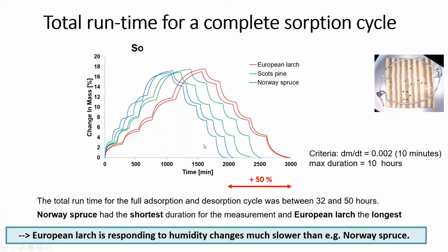Okay, so what I'm presenting, some of the highlights that you found that are quite interesting to think about. Like, how long does it take to complete a sorption cycle? So what she has done is she let the wood sorb at each stage a complete adsorption. If you look at the red lines, because they're quite well visible, now it goes from 20 to 40 and so forth to the maximum, and then it does the whole thing back. And then you just count up the complete duration of a complete sorption cycle. How long does it take? And is there any difference between, and here we are looking at the 3 softwood species we looked at.